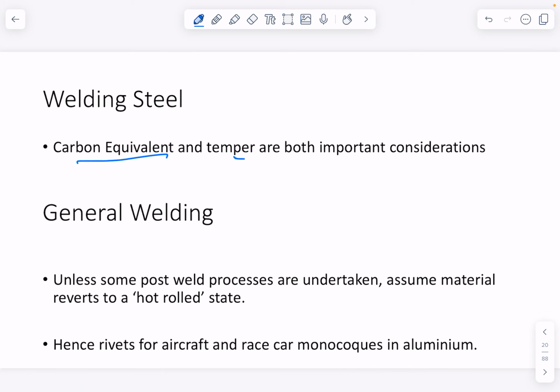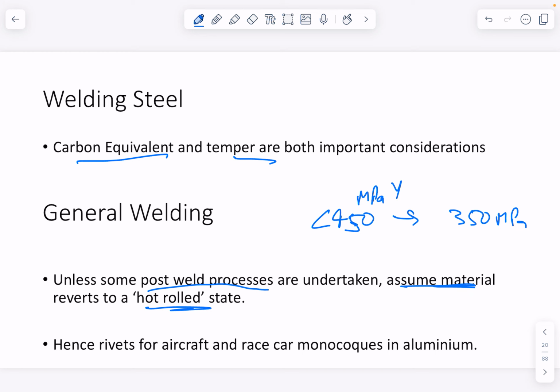As I said, carbon equivalent and temper are both important considerations. In general, unless you're going to do some sort of a post-weld process, you're going to assume that you're going to end up at a hot rolled state. So if I get a bit of C450 RHS and I weld it, then all of a sudden I'm down to a 350 MPa yield stress. So I've already lost quite a bit of strength in and around that weld. So hence I want to try and get my welds out of the highest stress zones if I can.